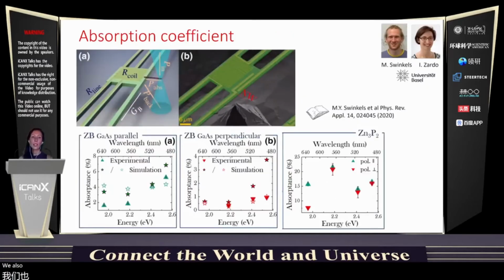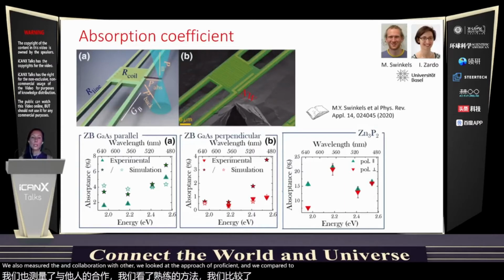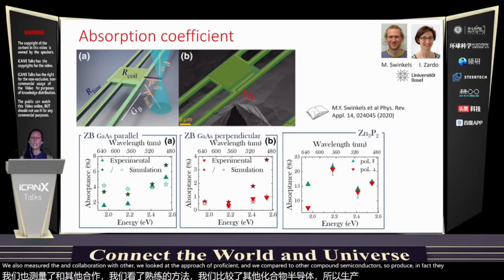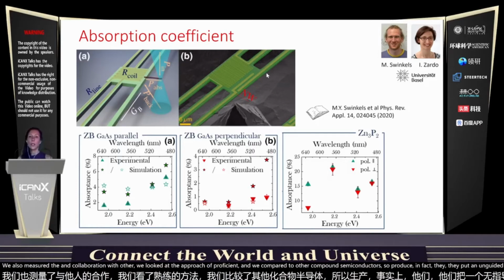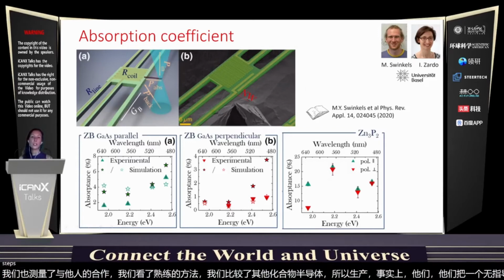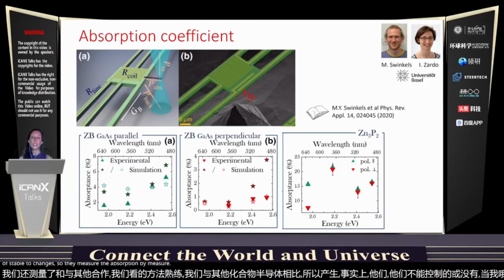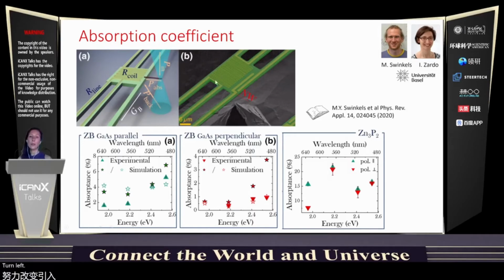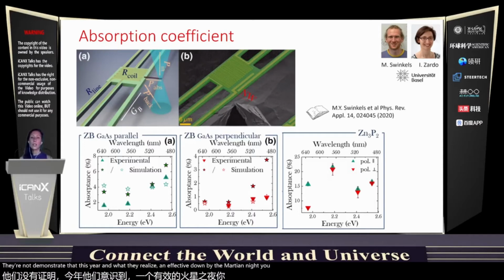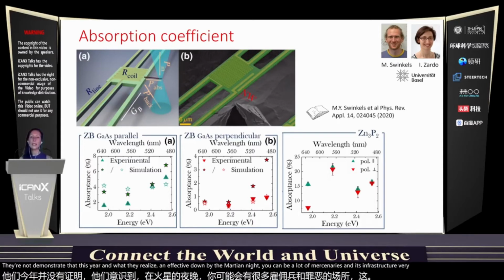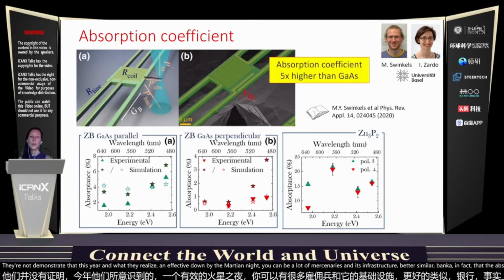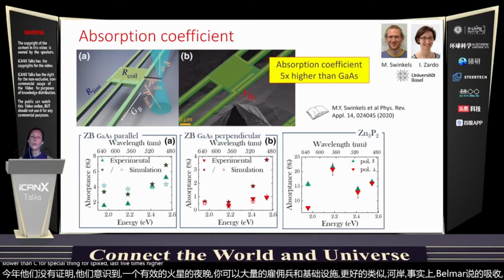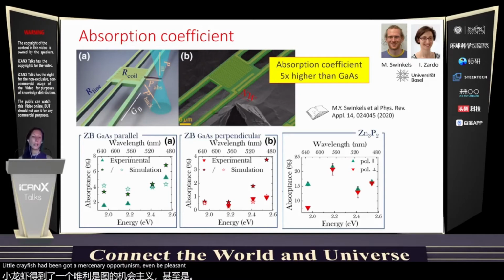We also measured, in collaboration with Ilaria Zardo in Basel, the absorption coefficient, and we compared to other compound semiconductors. For this, they put a nanowire on an apparatus that is suspended and measures temperature changes. So they measure the absorption by measuring the temperature change in this thermometer that is here. And what they realized is, if you compare gallium arsenide and zinc phosphide, which have very similar band gap, the absorption of gallium arsenide is 5 times lower than zinc phosphide. So zinc phosphide has 5 times higher absorption coefficient than gallium arsenide, which means that you even need less material to make a solar cell.